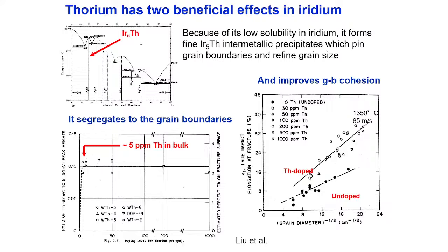And then if you plot the ductility, elongation to fracture, of all the undoped alloys versus all the thorium-doped alloys, and you can take thorium from 30 ppm all the way to 1000 ppm, what you find is all the thorium-doped alloys fall on one curve and all the undoped alloys fall on one curve. The reason I plotted this as a function of inverse grain size is because now you can separate out the intrinsic effect of segregation to the grain boundary from the grain refinement effect.